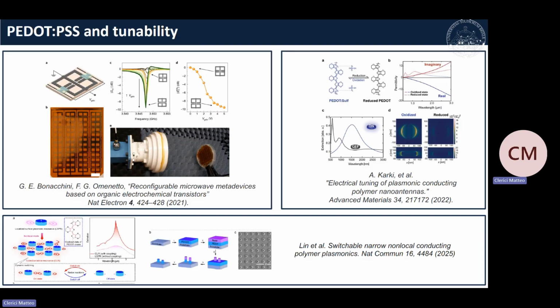The tunability of PEDOT has been proven in the microwave regime, but also in the visible and IR. And in particular, what has been shown is that you can tune a single element of PEDOT or a layer of PEDOT and change its refractive index properties from metallic to dielectric. So by applying an external voltage, you can change the refractive index by injecting or extracting those ion species from the adjacent electrolyte.